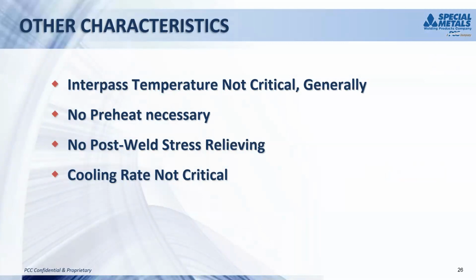Other parts of nickel alloy welding are not any more difficult than steel, and actually are simpler. Most nickel alloys, at least the solid solution nickel alloys, are single phase from melting all the way down to sub-zero temperatures. So interpass temperature is not usually critical. With the stainlesses, and those that tend to form carbides, it's much different. And steels that form multiple phases like martensite and cementite are much more critical than nickel alloys. Generally, with the solid solution nickel alloys, you don't need any preheat. And secondly, you don't need post-weld stress relieving.